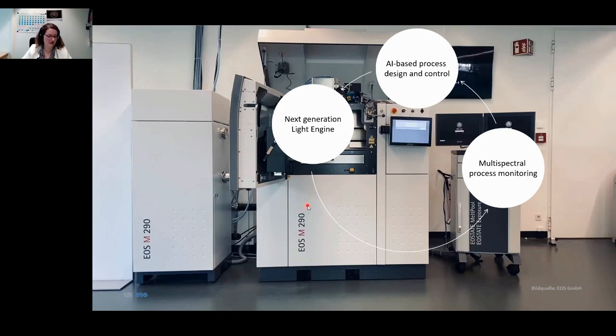In our case, we are mainly focusing at the moment on Inconel material and try to understand the influence of the different size of the beam shape and the different beam shapes on the process behavior and later on the component properties. And in the future, this is combined with this multispectral process monitoring setup. And the idea is then really to control the process based on the melt pool characteristics, the features, and the materials we have at the end.